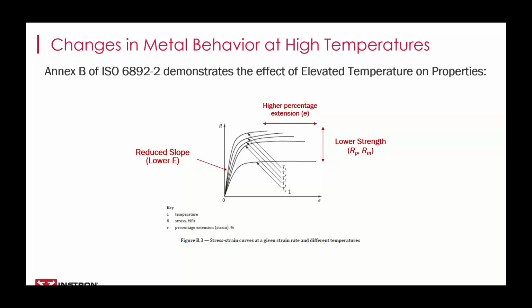Another thing that we see in high temperature testing is the results will typically exhibit higher elongation. This is because the softer material is more ductile. And so of course it'll exhibit less brittle failure than it would at ambient temperatures. The increased portion of ductile failure translates directly to longer elongation of the specimen.